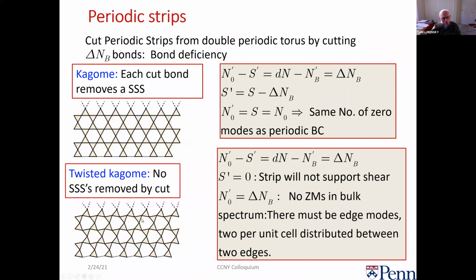Okay, so let's go to the twisted kagome lattice now. Now, when I cut the number of bonds, the states of self-stress stays the same. And so then I change the number of zero modes, which was not the case up here. Here, I don't change the number of zero modes. It stays the same. Here, I get more zero modes equal to the number of bonds I've cut because the states of self-stress hasn't changed. And so what that tells us is that for each site going along here, I get two extra zero modes, or that amounts to two modes per wave number.